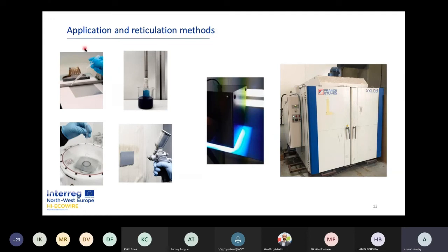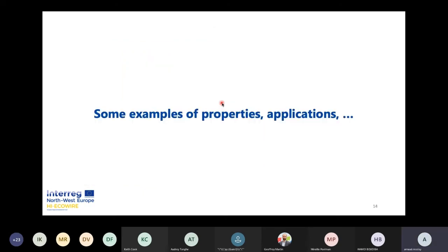The possible methods of application for coating can be barcoater or at the industrial scale coil coater, by dip coating, spin coating, or spray coating. And the curing method, the densification method, can also vary. This curing step is necessary in order to obtain the densification of the sol-gel matrix. At Hi-Ecowire, the curing step is generally carried out under heating. However, UV curable hybrid coatings are currently developed, where a mix of siloxane and polymeric chain are formed.